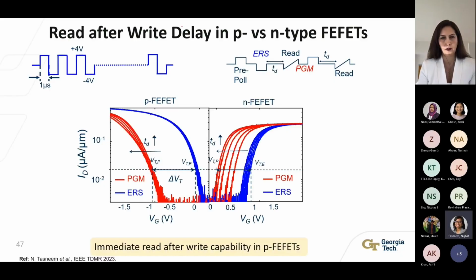So for that, we measured the read after write delay for both P and N-type FeFET. Now, in case of an N-type FeFET, we see that the memory window is significantly dependent on the read after write delay. And if we increase the read delay, the memory window also increases. On the other hand, in case of a P-type FeFET, the memory window is completely independent.